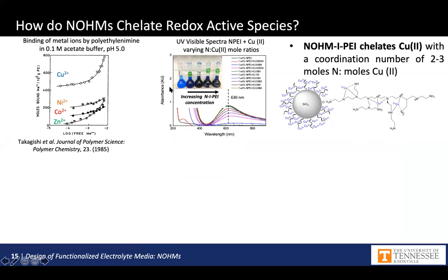So if we have copper salt in solution, which is shown in this little picture here, and we add NOHM-I-PEI to it, we see this dark blue color, which is characteristic of a copper amine complex. That gives us an indication that complexation was indeed happening. We were able to study this using UV visible spectroscopy, which gave us an indication of the coordination number of the amines towards copper, which we found to be about 3 moles of amine per mole of copper.